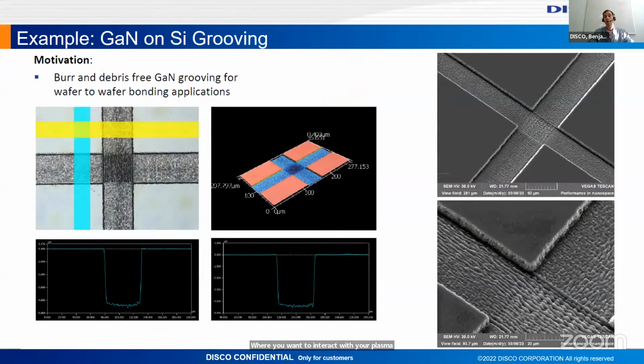One example I want to show you for a classical grooving process is here. Gallium nitride, wide bandgap material. For the grooving process itself, it's key to not create a significant thermal damage zone on your bulk material, because after the blade cut, this will reduce the mechanical robustness of the die to succeed in the subsequent process steps. But as you can see here, if the conditions are correctly chosen, then you get very clear and defined cutting edges, a very smooth surface roughness, defined grooving depths, and also for wafer-to-wafer bonding applications, it's important to have very little recast or burr, because this transfers then into a larger area that is not bonded on your device.